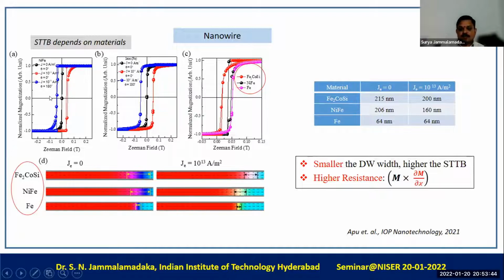So to understand more about more spin transfer torque bias in the iron system, we also took the snapshots of micromagnetic images. We do see a short domain walls for iron case in comparison with Fe2CoSi. That means that the DX term in the non-adiabatic spin transfer torque is very small. That leads to the larger value of m cross dou m by dou x, which leads to the higher resistance for the domain wall. Okay, so if the domain wall width is small, then the resistance will also be very high, because this dou delta x is in the denominator. That leads to high resistance for the domain wall.